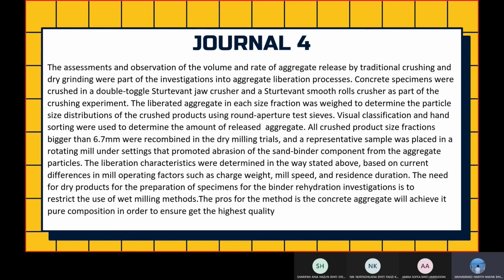All crushed product size fractions bigger than 6.7 mm were recombined in the dry milling trials, and a representative sample was placed in a rotating mill under settings that promote abrasion of the sand binder component from the aggregate particles. The liberation characteristics were determined in the way stated above. Based on the current differences in the mill operating factors such as charge weight, mill speed, and residence duration, the need for dry product for the preparation of specimens for the binder rehydration investigation is to restrict the use of the wet milling method. The pro of the method is that the concrete aggregate will achieve its pure composition in order to ensure the highest quality.